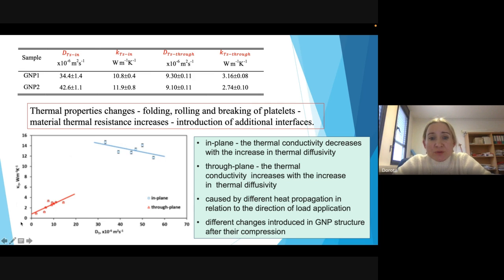In the case of through-plane properties, the thermal conductivity increases with the increase in thermal diffusivity, whereas in the case of in-plane thermal properties, the thermal conductivity decreases when the thermal diffusivity increases. Why is it like that? Generally it's like that.